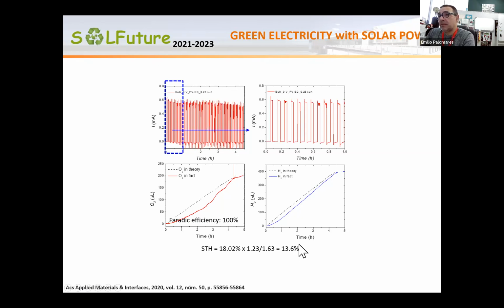And then after we published the paper, the people from Thomas Jaramillo at Stanford used a gallium arsenide solar cell with a similar ruthenium catalyst, and they surpassed this number. I think 15% is the record right now. So this is the Faraday efficiency in oxygen, what it should be in theory, and what we get. And this is in theory the hydrogen we should get, and this is in fact. So we know that it's not a perfect system, we have some leaks.